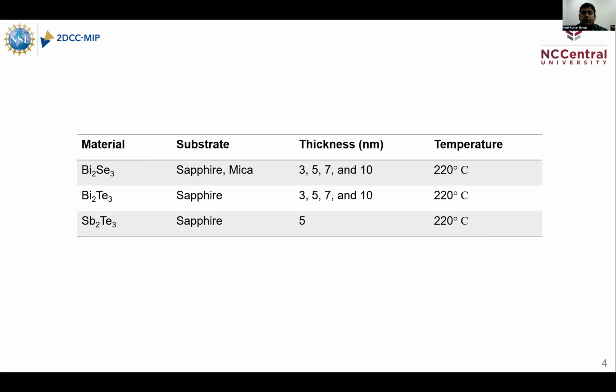So we grew bismuth selenide, bismuth telluride, and antimony telluride samples. We selected sapphire and mica substrates. For bismuth selenide and bismuth telluride, we grew 3, 5, 7, and 10 nanometer samples for our studies. We also grew a few samples for optimizing the thickness: 21 nanometer for bismuth selenide, and for bismuth telluride somewhere around 63 nanometer.